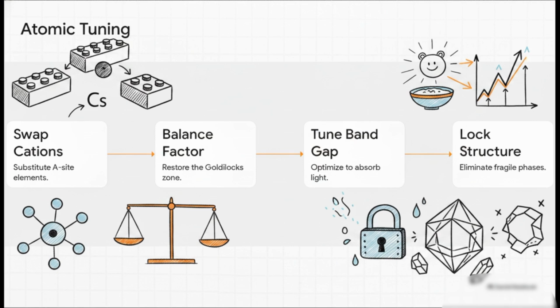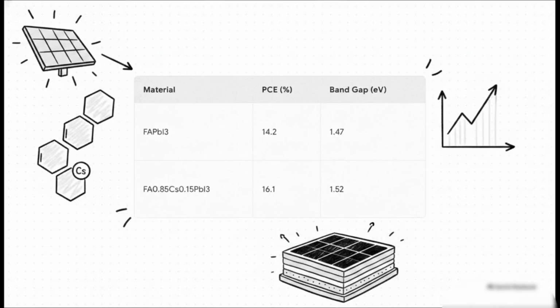Let's look at some actual numbers, because the concrete results speak for themselves here. A standard pure perovskite cell achieves about 14.2% efficiency. Not bad. But by swapping in exactly 15% cesium, scientists engineered a brand new molecular structure. That one tiny atomic tweak boosted the efficiency to 16.1% and perfectly stabilized the band gap at 1.52 electron volts. This is undeniable, real-world proof that tuning at the atomic level directly upgrades the power of the solar cell.